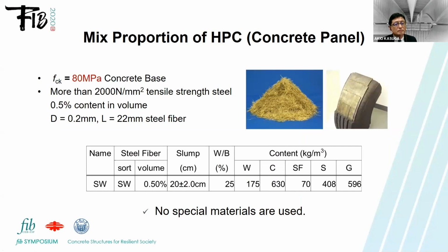This is a mixed proportion of the high performance concrete. And the compressive strength is 80 MPa, not so high. It's not so special concrete base. And also this is a fiber. The tensile strength is more than 2000 Newton per square millimeters, which is used in UHPC. And also the content is only 0.5% in volume. The diameter of the fiber is 0.2, and also length is 22 millimeters. So this steel fiber comes from the fiber from radial tire. So this is also not so special materials. So we can procure anywhere in the world where the tire factories are there.